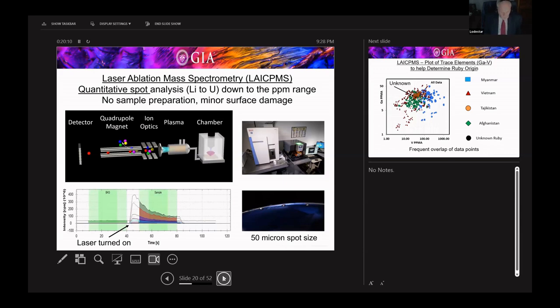We normally analyze several locations around the girdle of the stone, trying to pick areas where there's no color zoning in the sapphire or no prominent inclusions. When the laser fires, it removes small particles of material, and those are carried by means of a flowing gas into a high temperature plasma, and all the atoms in the material are ionized, and you can detect them with the instrument.